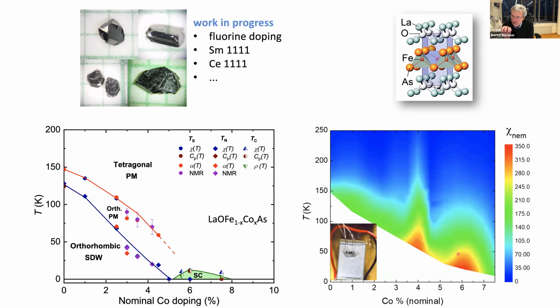Nevertheless, these very sensitive probes of the Fermi surface, so thermal power typically measures if you have a peak in the density of states or something like that. These are basically identical in these systems, telling you that this instability itself and also somehow the strain derivative, which is somehow still a little bit of coupling to the lattice, is very, very similar. So I'm absolutely sure that at the end of the day, this is an instability of the electronic system.